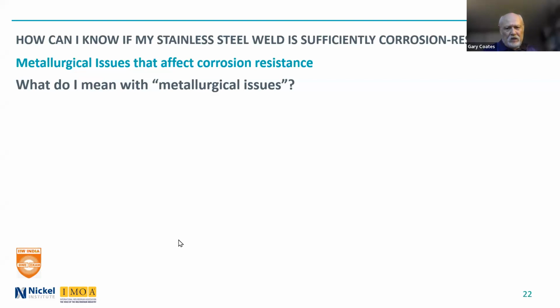Up to what temperature is the passive layer in stainless steel stable? Well, it's stable until it starts growing through heat, reacting with oxygen in the atmosphere, which can cause it to grow and therefore reduce corrosion resistance. I'd have to look at the temperatures we're involved with, but it's probably close to 650, 700 Celsius anyhow. Below that, it grows so slowly that it doesn't affect the corrosion resistance.